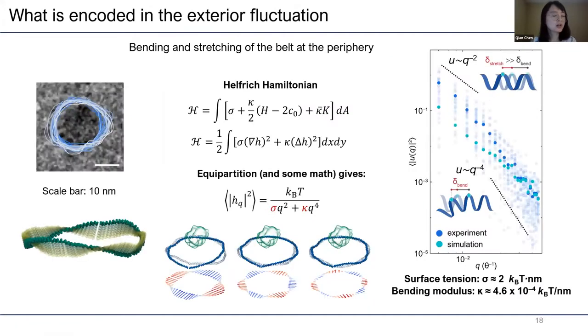We can also extract biological information out of these undulations of the exterior contour fluctuation of the nanodiscs. Shown here, we can decompose those real space fluctuations into a series of deformation modes in the reciprocal space. I'll skip the math, but just highlight one fact and one plot. The fact is, it turns out the elliptical deformation mode contributes predominantly to the fluctuation. The plot is shown here. The y-axis is the Fourier transform modes, and the x-axis is the wave vector.